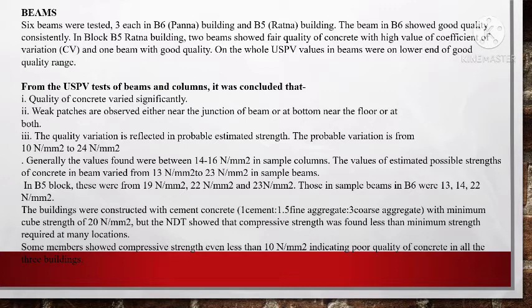The buildings were constructed with cement concrete. The ratio is 1 cement to 1.5 fine aggregate to 3 coarse aggregate. The minimum cube strength required is 20 Newton per mm square, but the NDT showed that compressive strength was found less than the minimum strength required at many locations. Some members showed compressive strength even less than 10 Newton per mm square, indicating poor quality of concrete in all the 3 buildings.